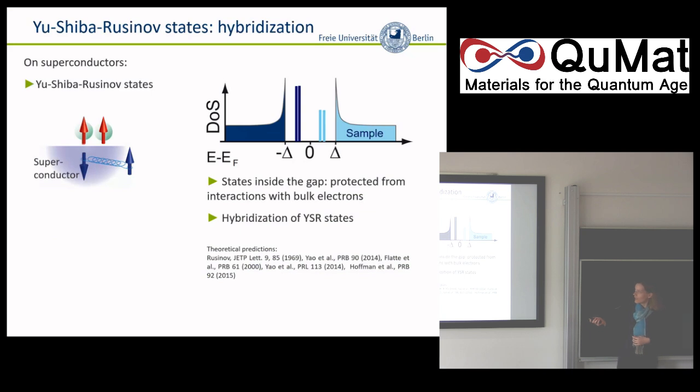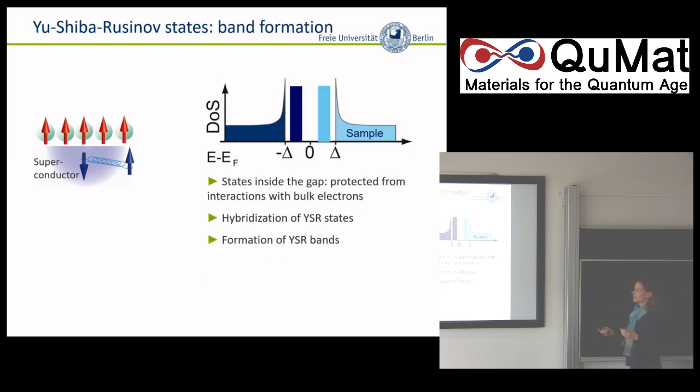But for instance, you could also say, let's say you want to put lattices, or let's say start with 2, similar to what is done here in the department. So basically, 2 atoms now, eventually these states could also hybridize. So you would see a splitting, or at least that's what you expect to see. Okay, it's not only two, well, one too many. So also, let's say you can eventually put up larger structures or chains, and then of course the states, I mean, you have hybridization, and at some point, first of all, your energy resolution will be insufficient to separate all the individual states, but eventually you would also get band formation.